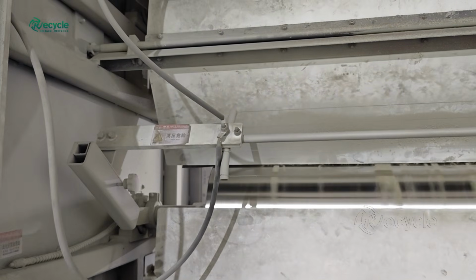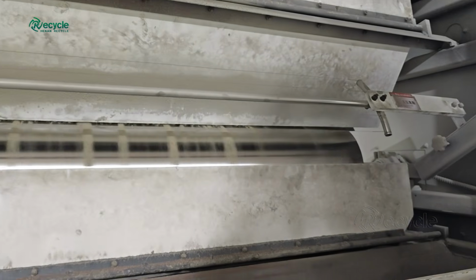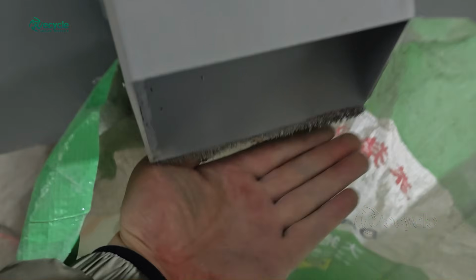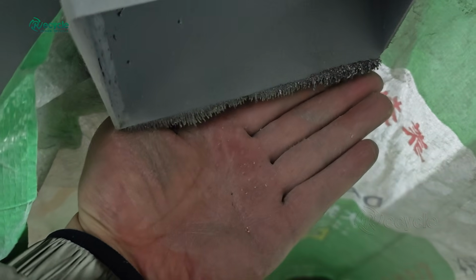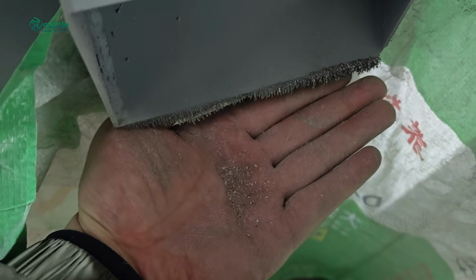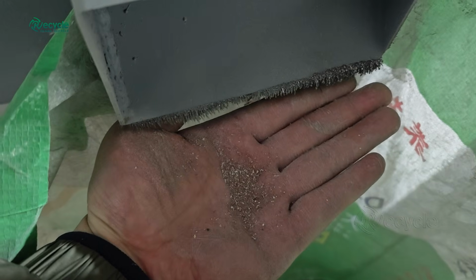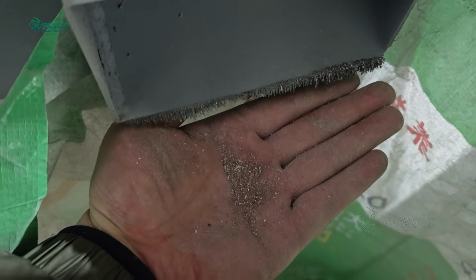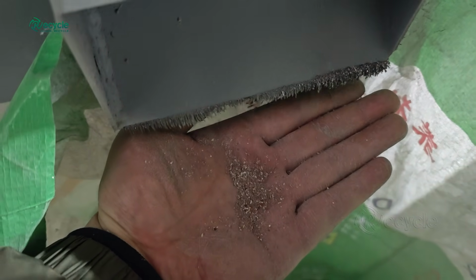Through this integrated process, the final products include high-purity copper and copper tin mixed powder, concentrated electronic components from the thermal dismantling stage, and low metal content resin and fiberglass powder. These outputs are highly favored by smelters and downstream processors due to their high liberation degree and stable quality.